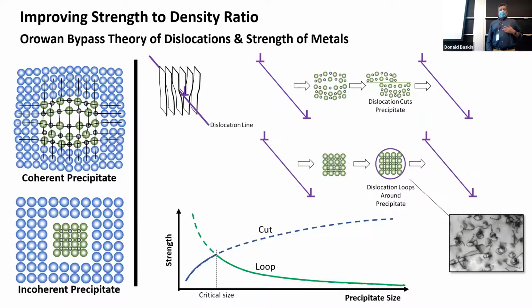We talked about this guy right here. When the precipitates are small enough and a dislocation is moving towards a precipitate in the material. By the way, the precipitate could be like a metal carbide, for example, what we call M2C. M is metal, C is carbon, so two metal atoms to each carbon atom. That's an example of a precipitate. The ones in aluminum, I think, are some kind of aluminum silicide, or magnesium silicide. Anyway, when the precipitates are small and a dislocation is moving towards them while the material is being deformed, once it gets to the precipitate, it's energetically favorable for the dislocation to actually cut the precipitate in half.